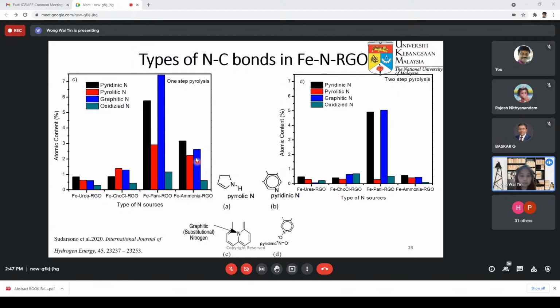Here, if you compare the 4 types of catalyst, the Fe-PANI, PANI is actually a polymeric type of precursor, hence the nitrogen content is relatively high as compared to others. Okay, you can see that for this PANI, the pyridinic and graphitic pyrrolic nitrogen content are very high, followed by the Fe ammonia. But upon second pyrolysis, as mentioned, the nitrogen content has greatly reduced, especially on the 3 other samples, except that for PANI, the atomic content is still quite high. And also there is a reduction in the pyrrolic N, but there's a maintaining in the pyridinic and graphitic N, okay, itself. But the rest, they actually drop.